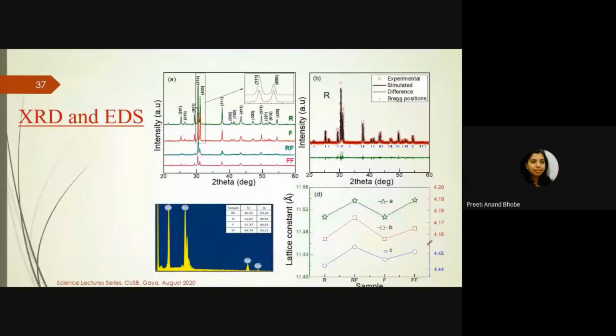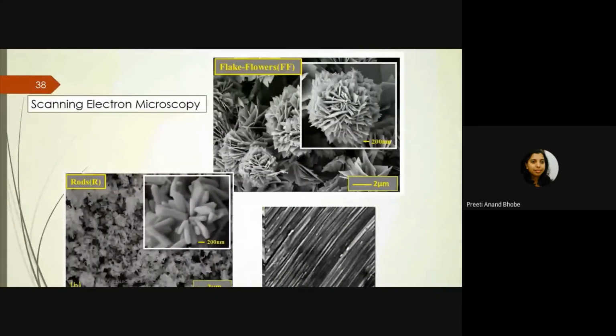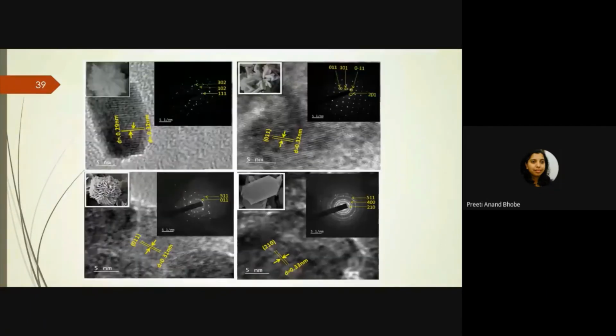If I see the XRD also, very pure, clean samples were obtained. Stoichiometry was very fine, as seen from EDX and all, and the lattice constant change also was as per reported. Scanning electron microscopy showed us that the layered structure of this material is maintained, and one gets nice flowers, rods, all morphologies, beautiful looking, even under a TEM. One gets a nice single crystalline form for the rod samples, or hexagonal crystals we see in the flowers. And the rod flowers showed us two different orientations of the rods. So all this was pretty good.